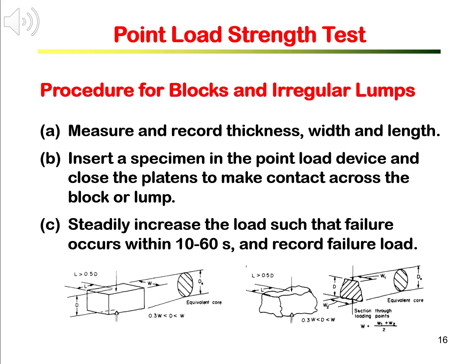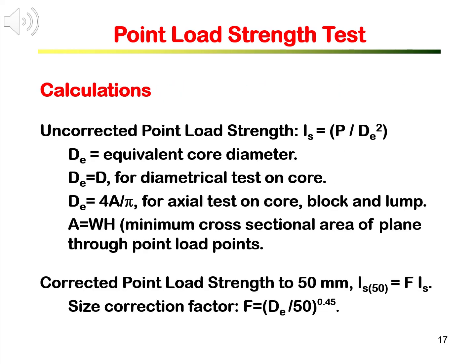The loading procedure is the same as before. After inserting between the loading platens, apply load steadily to break the block in 10 to 60 seconds and record the failure or peak load. On point loading, the lump specimen breaks across between the two loading points.